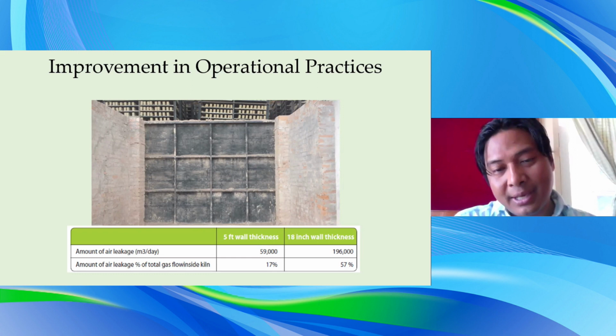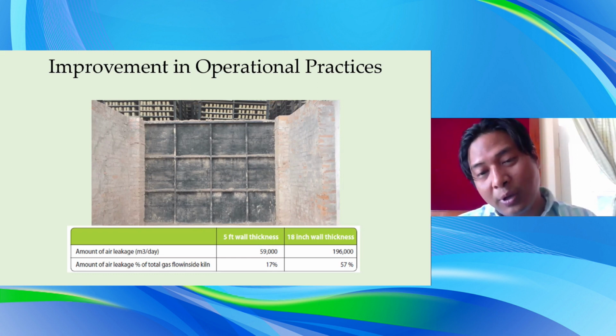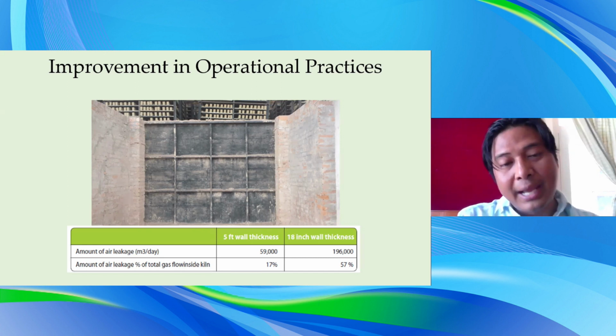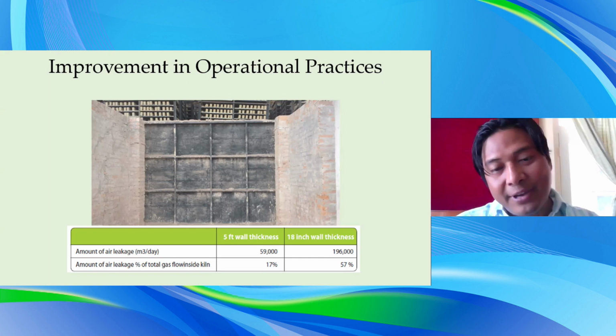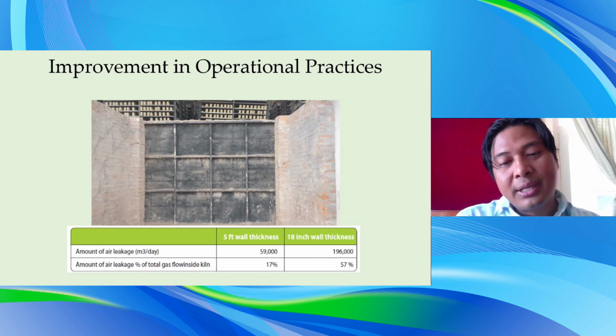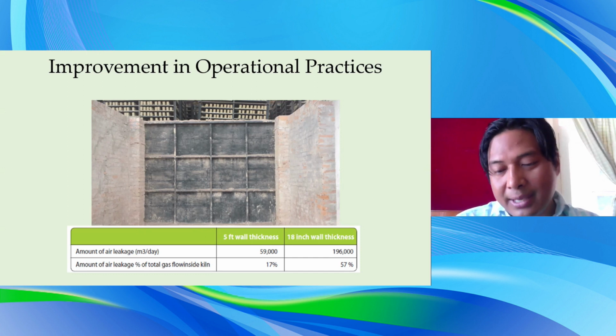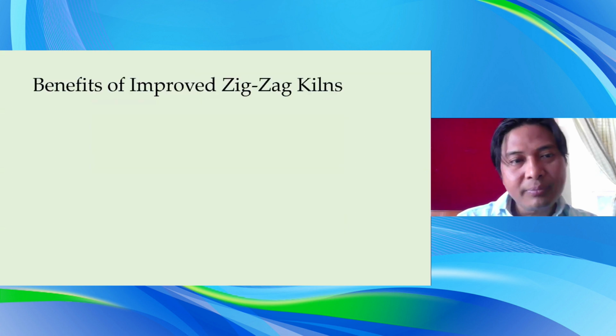You can also see in the figure that if we have only an 18-inch thick wall, which is the general practice in Nepal, the amount of air leakage is 57% from that wall. Whereas if we put in place the improved kind of wicket gate with a 5 feet wall, then we can reduce it to only 17% of air leakage from that wicket gate. That is one kind of improvement that we did.